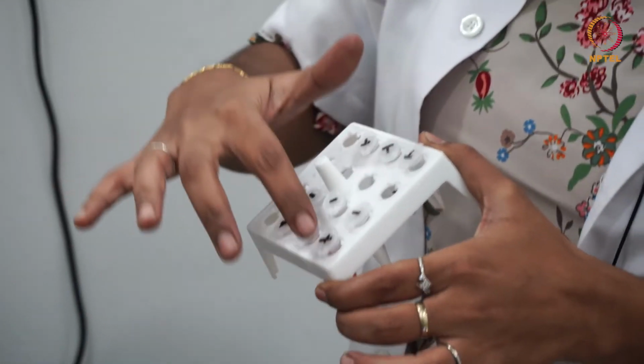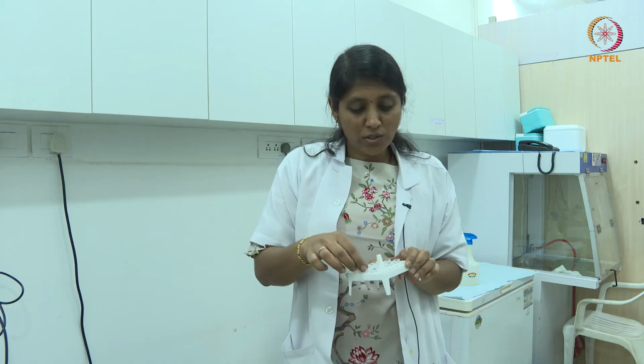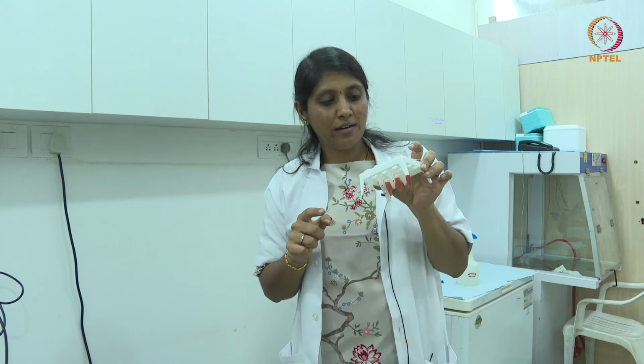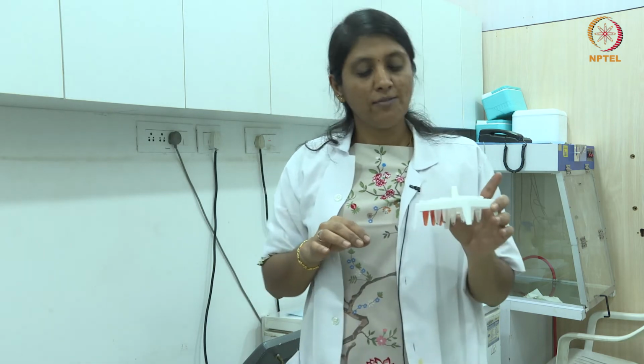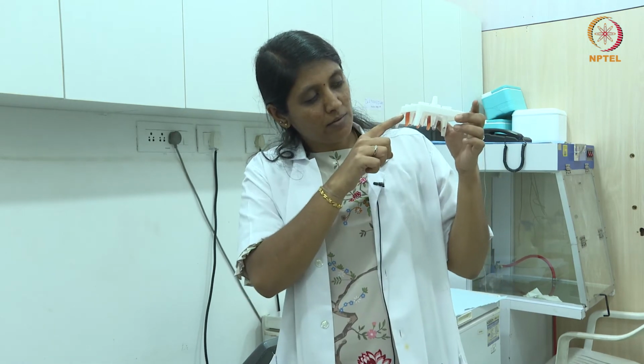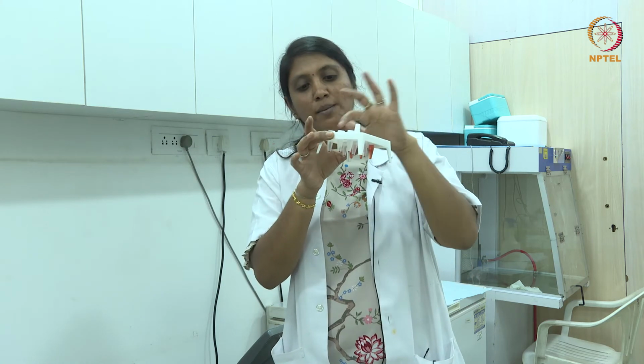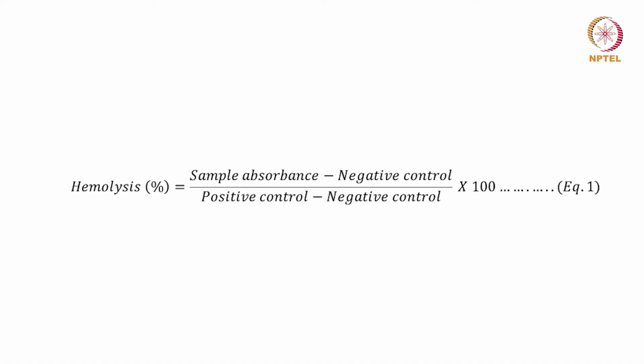Now after incubation, we have collected 3 positives, 3 negatives, and 3 test samples. Bioactive glasses were used as the test samples. Now we have to quantify the erythrocyte rupture rate in a UV visible spectrometer at the wavelength of 540 nanometers. Finally, we have to take the solution and analyze the absorbance, that means the optical density, in a UV visible spectrophotometer at 540 nanometers. That will give the absorption of the solution. With that, we have to plot a graph, hemolysis versus test concentration. With that formula, we have to analyze the results.